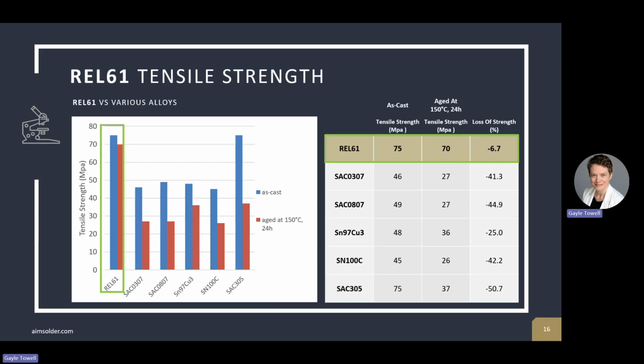This is one of our favorite tests, shows the difference in tensile strength, and we are comparing that strength when the alloys are first cast versus after they have been aged for 24 hours at 150 Celsius. What we notice is that as cast, REL61 and SAC305 have the same tensile strength, and both are stronger than the other alloys tested. However, after aging, REL61 maintains its tensile strength, only dropping very slightly compared to all of the other alloys, including SAC305, which lost about half of its strength.